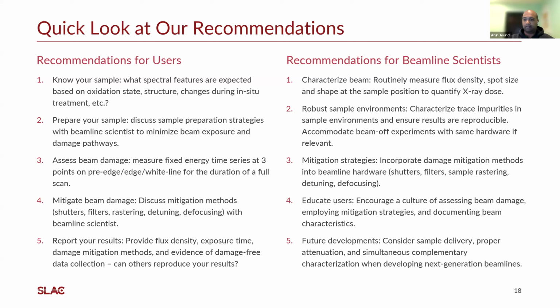Yeah, I agree with that. And a nice benefit of that strategy is that if the sample is damaged very quickly, doing a quick XAS or XANES scan may not reveal the damage if the damage is occurring even at the first data point. So choosing an energy that is very sensitive, like on the edge, and measuring as a function of time is more likely to reveal if the sample is damaged very quickly. Yeah.